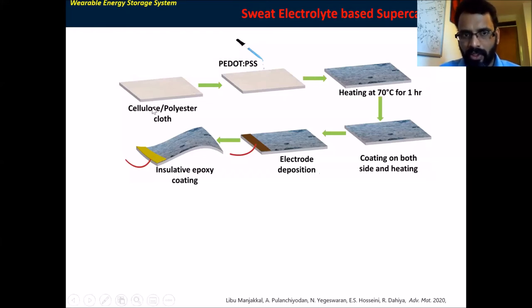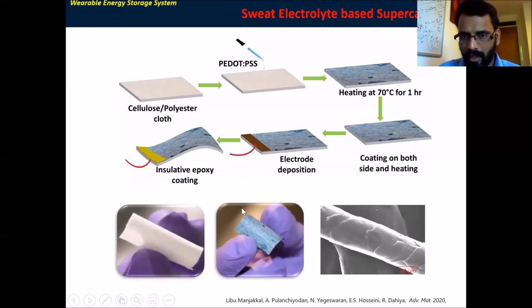What I used: I have a cellulose polyester cloth, and I converted that non-conductive cloth into a conductive one by using PEDOT:PSS conductive material. You can see here, it's a low temperature process. And then it is coated on both sides, then the electrode is deposited, and then stacked. You can see here an insulative epoxy applied on the electrode deposition. Here you can see the device, an image of the cloth, and then a fiber. Each fiber in the cloth absorbs the electrolyte, and it is equally distributed on the cloth fiber.